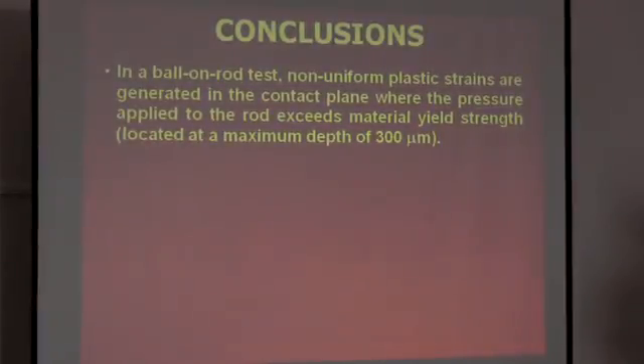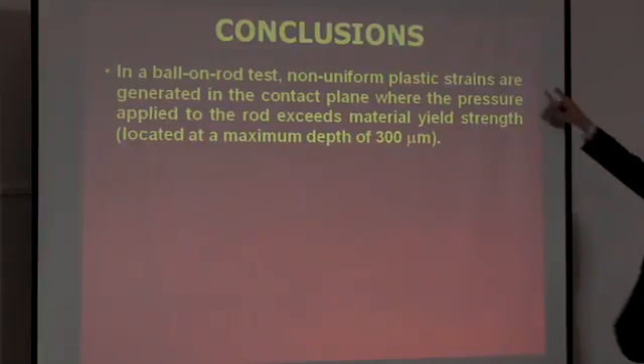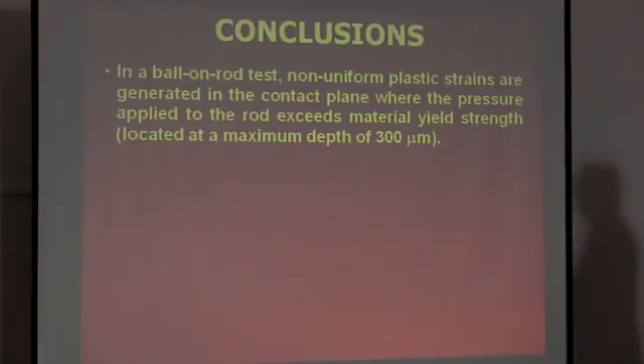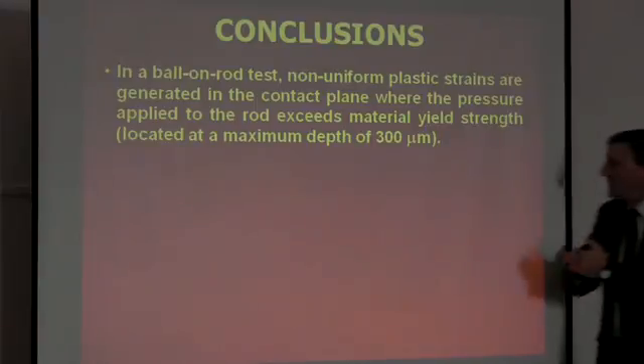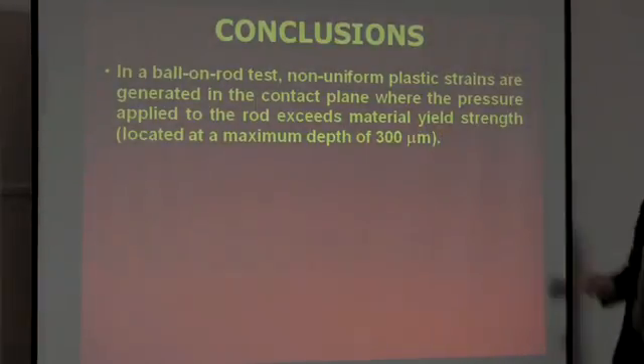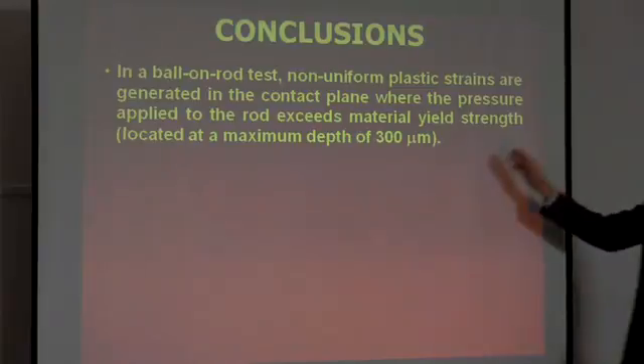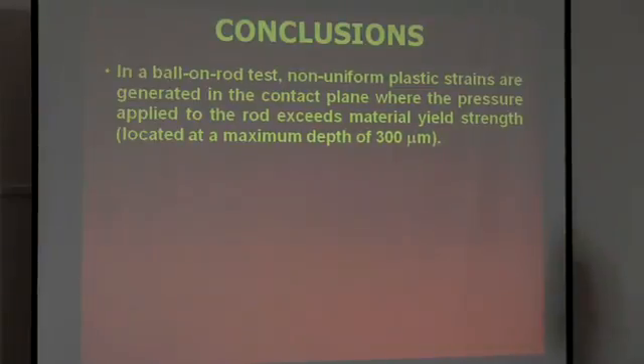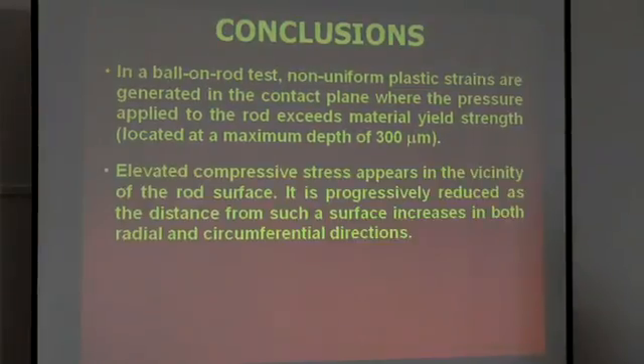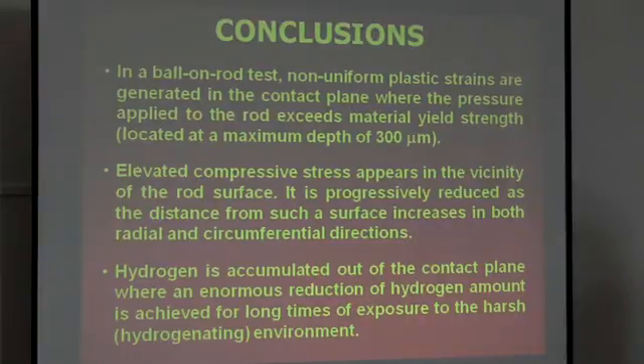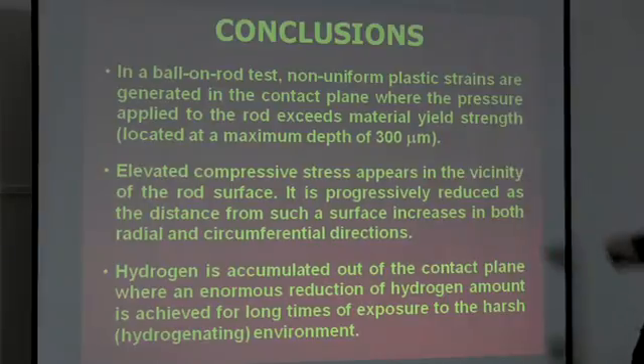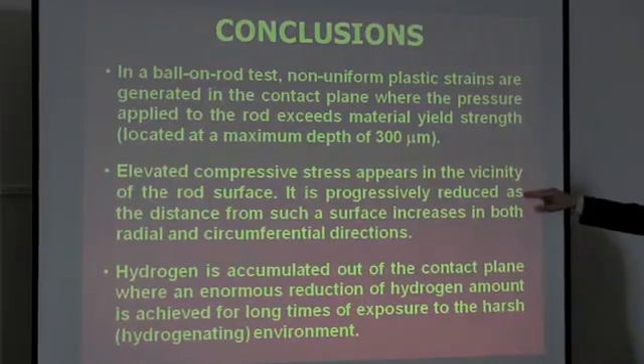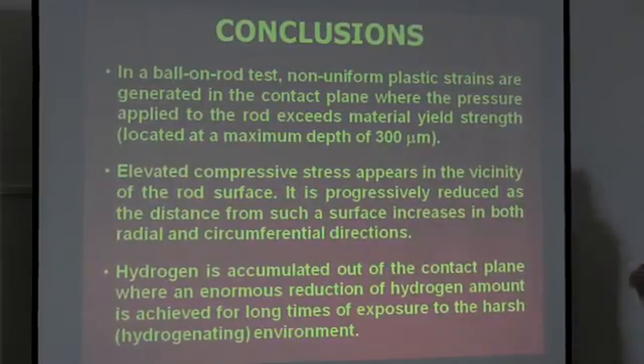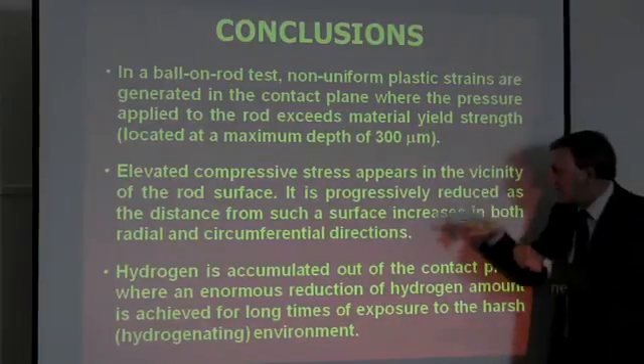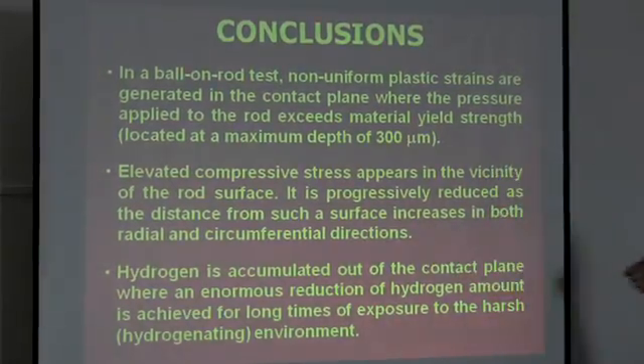In a ball-on-rod test, non-uniform plastic strains are generated in this contact plane where the pressure applied to the rod exceeds the material yield strength, located at a maximum depth of 300 micrometers. Elevated compressive stress appears in the vicinity of the rod surface. It is progressively reduced as the distance from such a surface increases in both radial and circumferential directions.